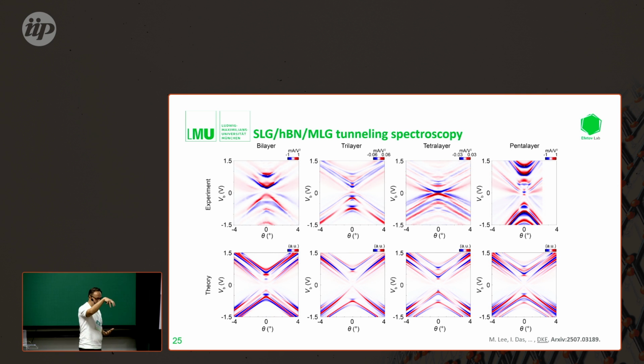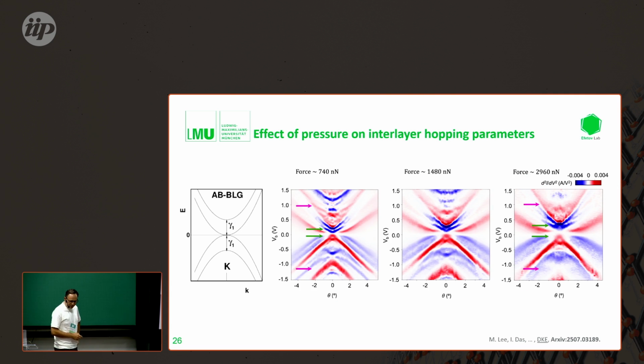And if you basically use a single simple tip structure from which you tunnel, you can, from all these measurements, reconstruct the band structure of the material, and you can define band structure parameters and so on. And of course, for multi-layer graphene, this is more or less known. You can do this for ABC, for rhombohedral graphene, where I think maybe band structure constants are not entirely clear, especially as a function of displacement field. So we're doing this right now in the lab. And this shows a little bit the spectroscopic power of this technique.